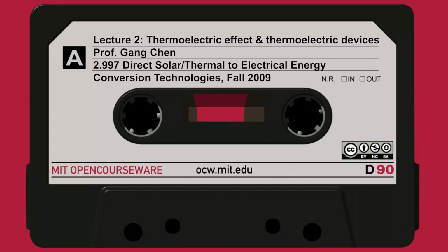And this Z, again, this is all coming from this mathematics, doing derivative. And it's the Seebeck difference of the two materials. And the denominator is the thermal conductance times electrical resistance. So you look at it, it's not a material property at all. It includes the material properties, Seebeck coefficient, electric resistivity, thermal conductivity, but it also depends on the cross-section area.